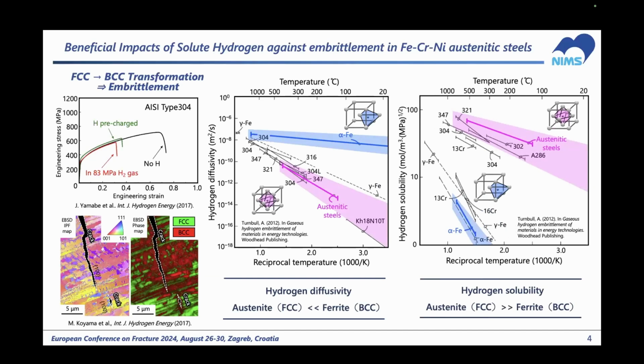Another notable property of austenite is the large solubility of hydrogen compared with ferrite. If we expose this kind of material to a gaseous hydrogen environment, it easily absorbs more than 100 ppm of hydrogen. So my talk is to explain how such a large amount of dissolved hydrogen in austenite changes the mechanical properties when the martensitic transformation is suppressed.